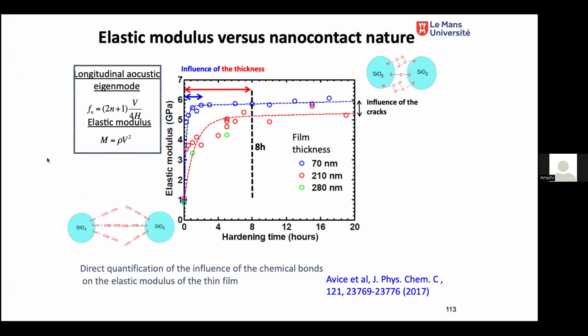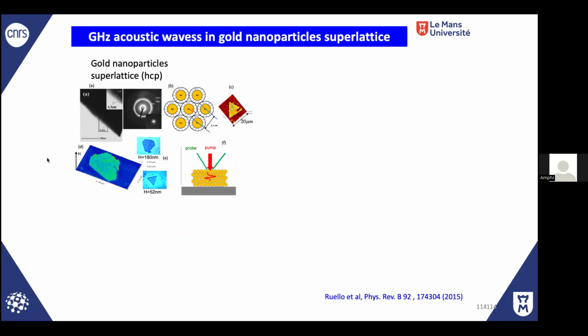So basically, this is one example. We look at assemblies of particles like that. The material is just made of an assembly of particles like that, deposited on a surface. With pump probe, you can induce some, so basically there are particles of 4 nanometers, like a supercrystal. So you can also induce coherent acoustic phonons in such layers. So these gold particles are connected by, let's say, covalent or van der Waals bonds.